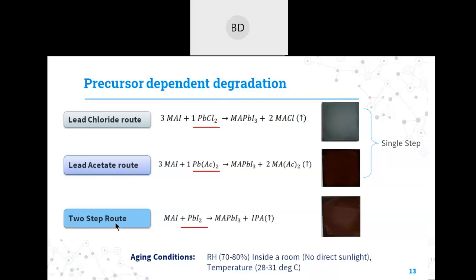And the third one is the two-step deposition route, where we have used lead iodide as a salt. All these three routes give the standard MAPbI3 structure. Although their byproducts are different, the structure is the same MAPbI3. I mean, the compound is perovskite. And these three films, deposited from these three routes, are put under degradation conditions like relative humidity of around 70 to 80% inside a room.